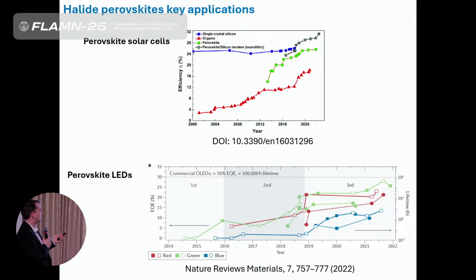Perovskite solar cells, which have now become very high efficient. You see, if you compare this blue curve, which is actually like a straight line, without any progress, for silicon, with the rapid growth of efficiency for perovskites. Now perovskite solar cells with a single junction are higher than silicon, and if we consider perovskite-silicon tandems, efficiency is now more than 33%. We know about many startups and some companies in Europe and China, and we believe that in the near future some companies will commercialize solutions for perovskite solar cells.